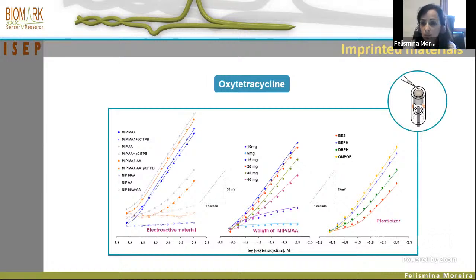The overall electrochemical performance of the biosensor was studied by potentiometric transduction. Several parameters were optimized, such as the composition of the membrane, the amount of the sensor, and the type of mediator solvent incorporated in the membrane. The best operational features were obtained when we co-polymerized the material with methacrylic acid, when we used 10 milligrams of the sensor, and when we used ortho-nitrophenyl octyl ether as a solvent mediator.